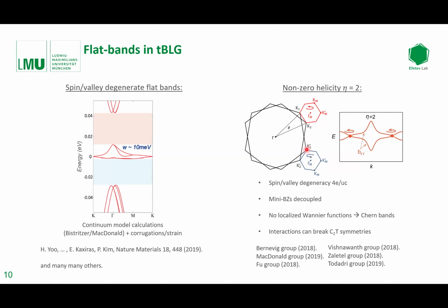And the other one is purely made out of the K prime points in the individual graphene layers. So that means that really, if you look at the Brillouin zone individually, they have net positive helicity or Berry curvature in the individual unit cell Brillouin zone, and then in the other one, it's exactly net negative. So if you integrate your Berry curvature over these mini Brillouin zones, you will actually not cancel the different contributions from the K and K prime points, but you would end up with Chern numbers of 2 or -2 individually.